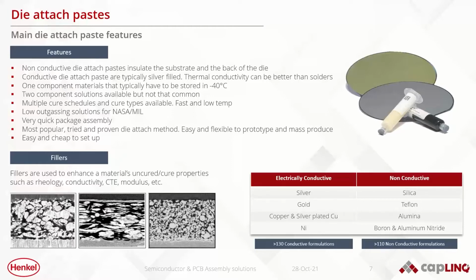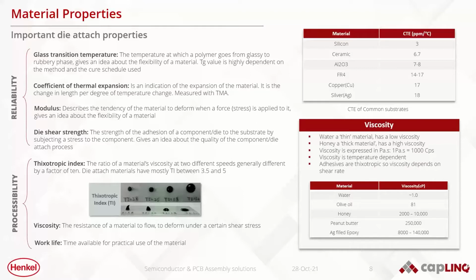When we talk about electrically conductive fillers, we talk about silver, which is primarily what's used, but there are also gold, also copper and silver plated copper, as well as nickel in some die attach materials. On the non-conductive side, the most traditional material that's used is silica. Silica being non-conductive, but it's also quite abrasive, or it can be abrasive. So in applications that need lower stress, or for applications that might be die stacking, Teflon is often used in these cases. When I say non-conductive, I mean non-electrically conductive. Other fillers such as alumina, boron, and aluminum nitride allow the material to be thermally conductive while still maintaining electrical insulation.